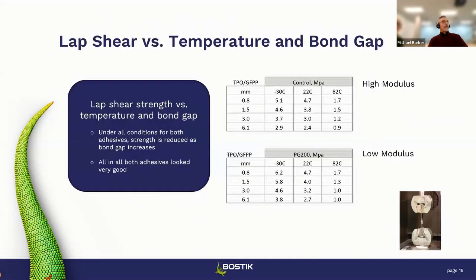And so our first example here is we're going to take these substrates. We're going to bond TPO, which has got no glass in it, to glass-filled polypropylene, and we're going to vary the bond gap. And so when we vary the bond gap, we're going to pull a lap shear at -30, at 22 and 82 centigrade, and compare the strength values of the control, which is the high modulus, to the low modulus adhesive. And without going into a lot of detail here, the numbers are very similar. So when we saw that, this did not align with the FEA model that we had generated. So we scratched our head and said, so what's the advantage of a low modulus adhesive in these applications?